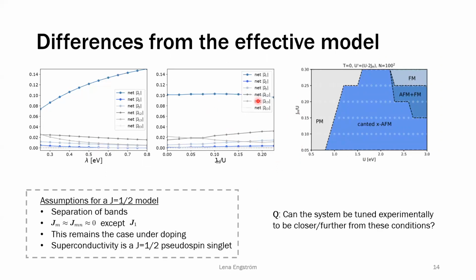What we can see then, if we use this full model and consider different components, that is, what different order parameters contribute to this state, is that the clearly most dominating one is from this J1/2 band, which are these pseudospins. This is what we expect because they are closest to the Fermi surface. However, we do have contributions from other order parameters, and we can change how much they contribute by changing the interactions. You can also see that by increasing or decreasing the spin-orbit coupling, for which we also have some approximate value, this band becomes more or less dominating.